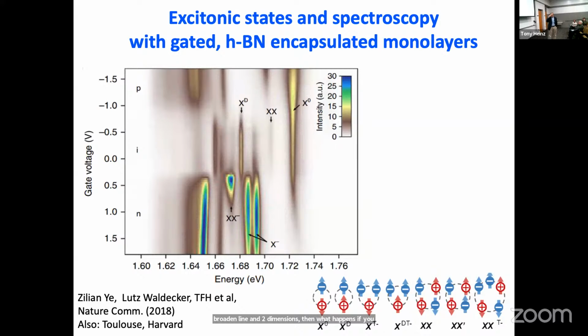So, at least for people looking at optical properties of solids, you always start by saying, well, there's some penetration depth, and that penetration depth is typically on the order of a wavelength. So a thin layer of nanometer, yeah, you'll perturb things, but not too much, a few percent. And famously, graphene has an absorption of 2.3%. But that's very far from a radiatively broadened line. So what would happen if you're resonant with the radiatively broadened line? Anyone like to hazard a guess here?